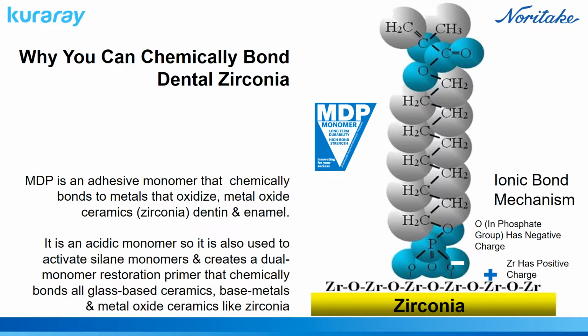What you have is, when you air abrade the zirconia surface and the inside of your restorations, you're going to expose some of the zirconia atoms, and then you have the phosphate atoms here that are negatively charged. They have a positive and negative charge, and they have a high attraction towards one another, and you get an ionic bond. So this is your ionic bond mechanism, and the reason you can chemically bond to zirconia as long as it's properly air abraded.